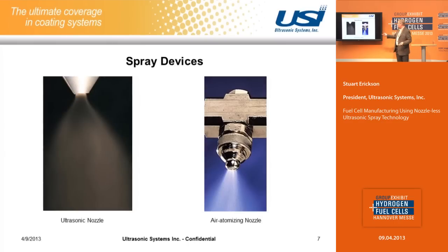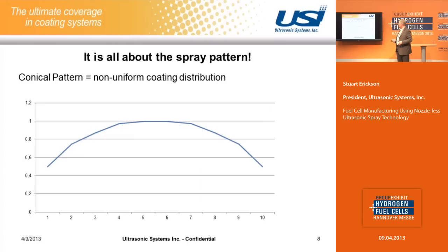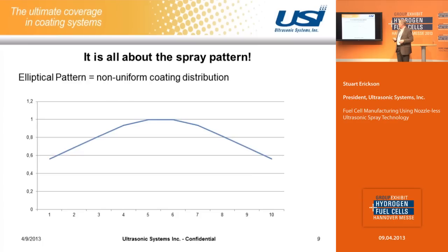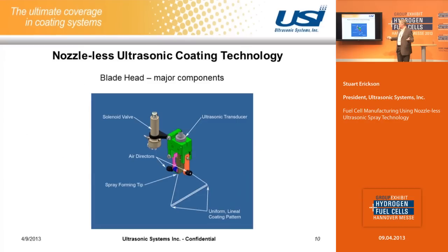Some pictures of an air atomizing nozzle or an ultrasonic nozzle. Typically what happens is, if you have a conical spray pattern, if you look at the coating distribution across from the center of the coating pattern applied by the nozzle, it's heavier in the middle and lighter on the edges. So a circular or conical pattern will produce that type of coating distribution. An elliptical pattern will produce a similar coating distribution with heavier coating in the middle, lighter on the edges.